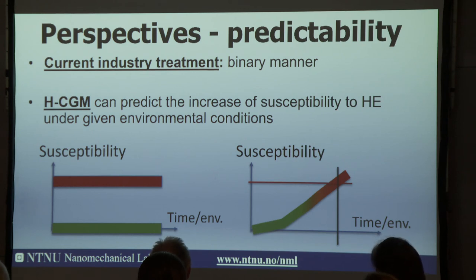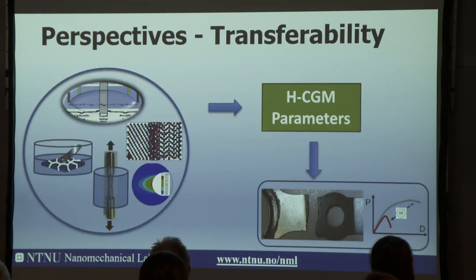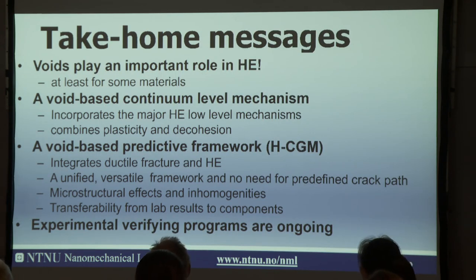Perspective: with the HCGM, we can predict the evolution of the susceptibility of the material. We can determine the HCGM parameters for the transferability. Okay, this is my last slide. We have proposed a void-based continuum level mechanism. It incorporates all the major lower-level hydrogen embrittlement mechanisms. It combines the plasticity and the decohesion. It integrates the ductile fracture and HE. This is very special. And we can enable the transferability from lab to the components. Thank you.